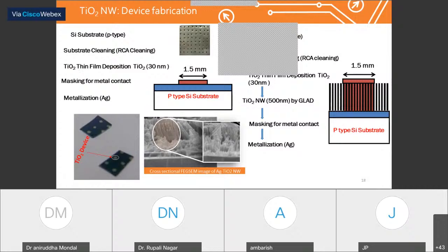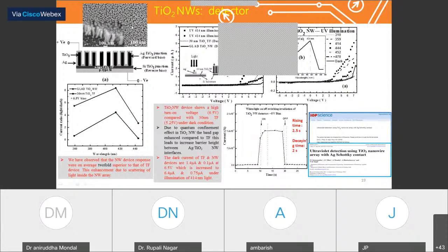A photodetector made of any kind of nanowires has a very fast response as compared to the bulk materials used for photodetector fabrication. We have used the following procedures to fabricate this kind of photodetector. You can see the cross-sectional images of these nanowires. These are nanowires made of titanium dioxide with azimuthal rotations of 100 RPM. These are the titanium dioxide nanowires directly grown on the silicon substrate.